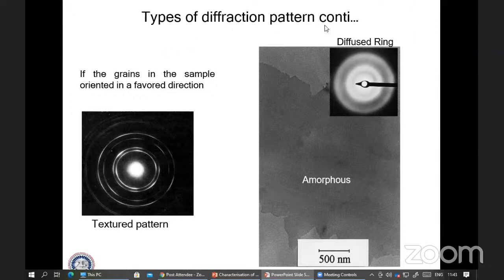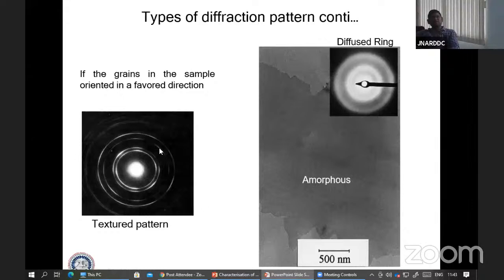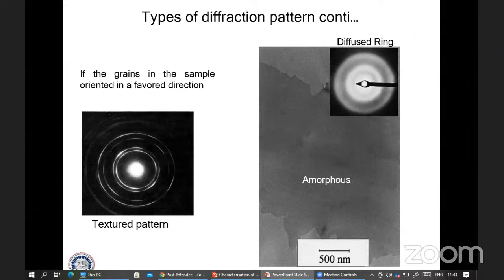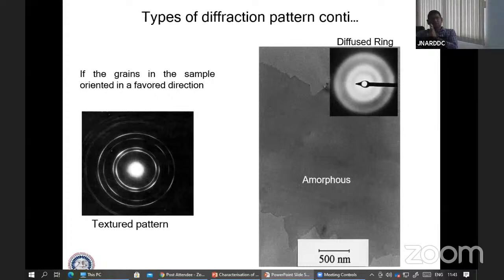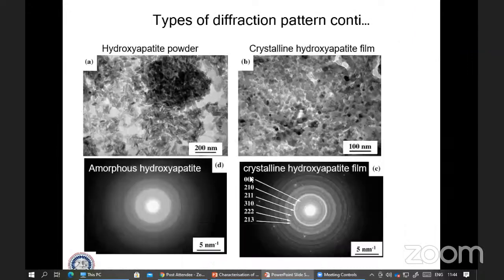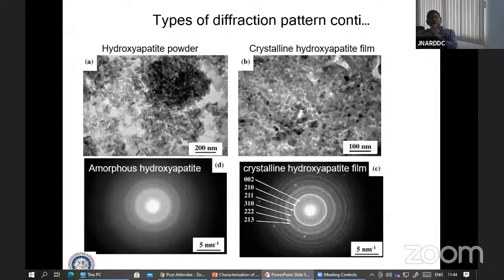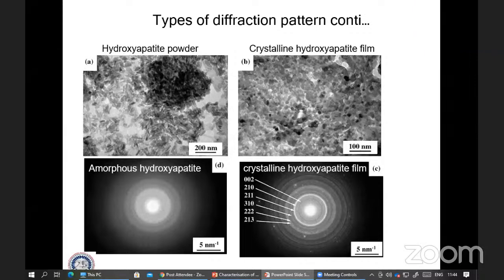Here are the types of diffraction patterns. Some are textured patterns. Why does the texture come? Because if some grains are oriented in a similar direction, one spot will have an arc-like shape, so you will have a textured pattern here. Suppose your material is amorphous, you get a diffraction pattern like a diffused ring pattern. And if your material is half amorphous and half crystalline, you will get a spotty ring pattern.